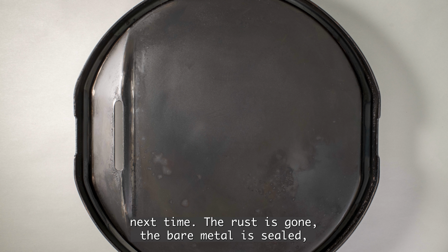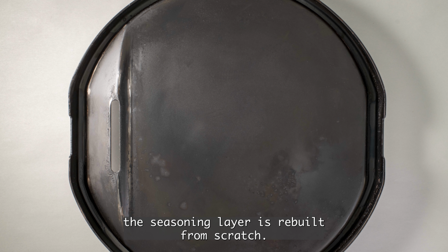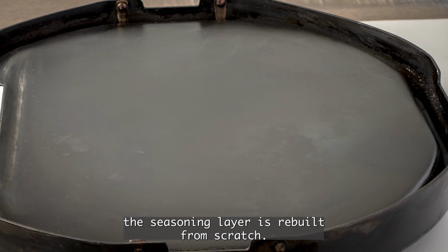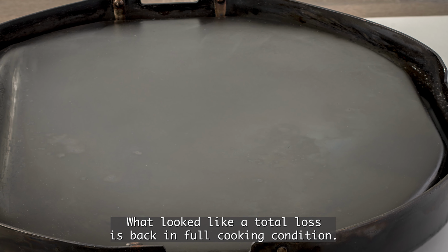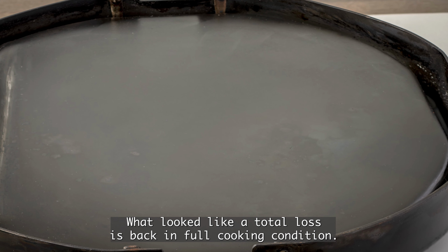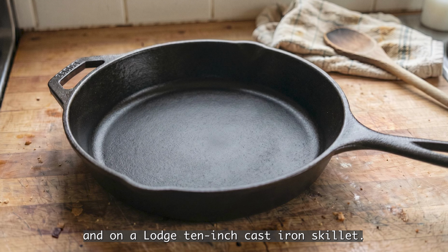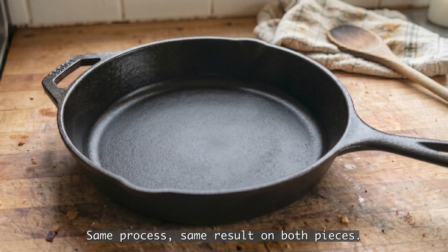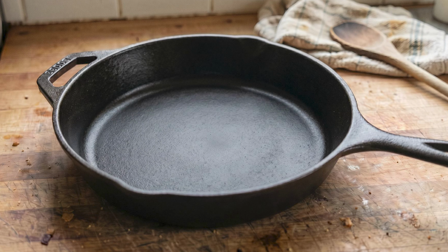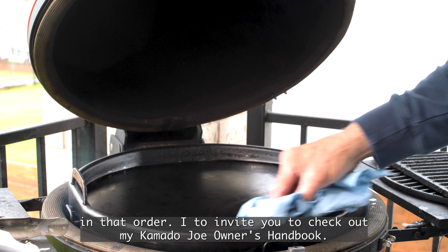The rust is gone, the bare metal is sealed, the seasoning layer is rebuilt from scratch. What looked like a total loss is back in full cooking condition. I've done this process on the carbon steel griddle you've been watching in this video and on a Lodge 10-inch cast iron skillet. Same process, same result on both pieces. Whether you're restoring a cast iron skillet your grandmother left you or a carbon steel pan you use every week, mechanical removal, chemical neutralization, full reseason, in that order.